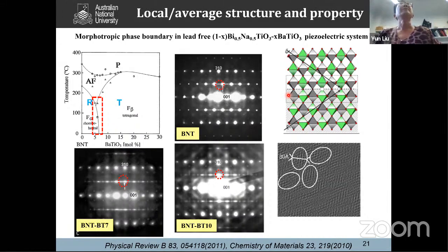However, if we find you have a little bit of spots here as a half 110, it is because this rotation you have a stacking fault. Actually, this rotation is stopped. So gray, you got a gray, and a green, green. So here is like a mirror, got a twinning of the stacking fault of the octahedral tilt. So in that case, this area corresponds to the high resolution image of structure. You got a few nanometer correlation length area.